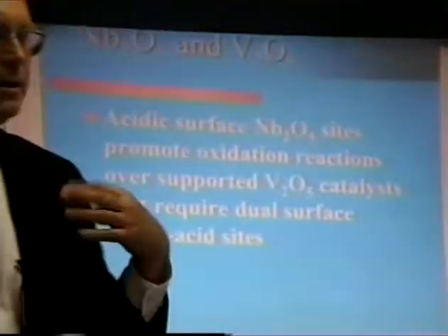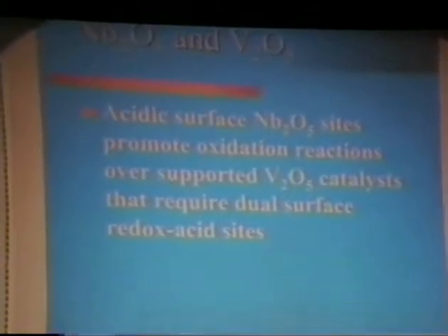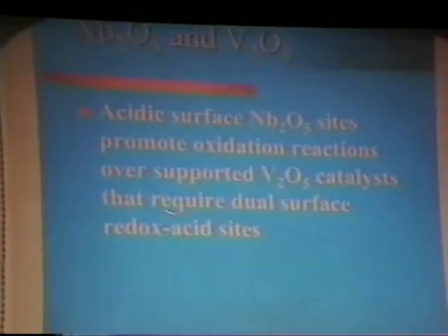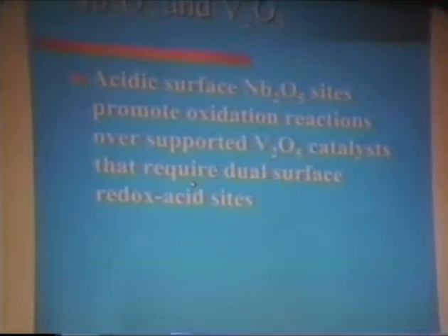In practice, the acidic surface sites of niobium promote reactions, in this case over supported vanadium catalysts, that require dual surface redox and acid sites. Let me explain maybe a little more what that means. Niobium is not going to be a redox catalyst in and of itself. Okay? It has acidity, and some fairly strong acidity. In something like a selective oxidation reaction, butane to maleic anhydride is one example, you will get promotional effects from the niobium.